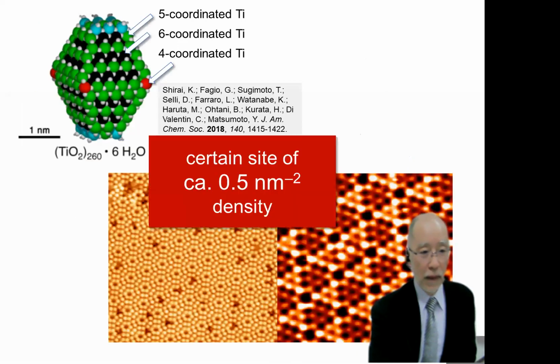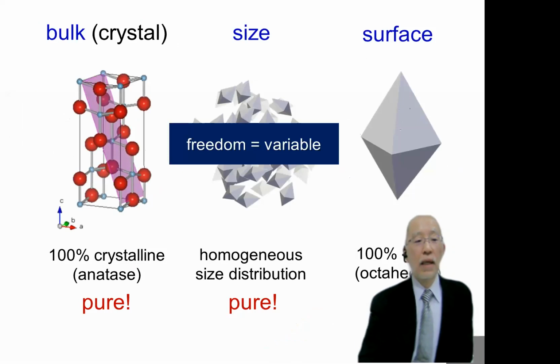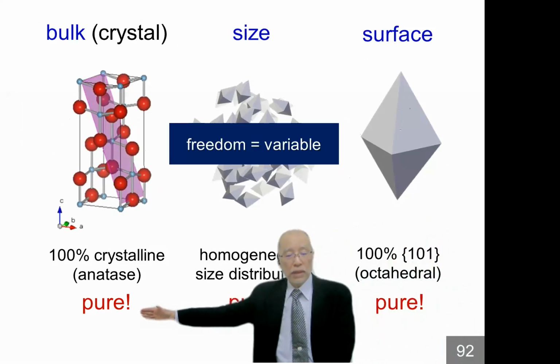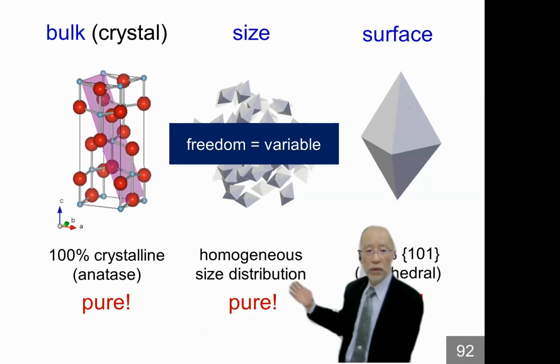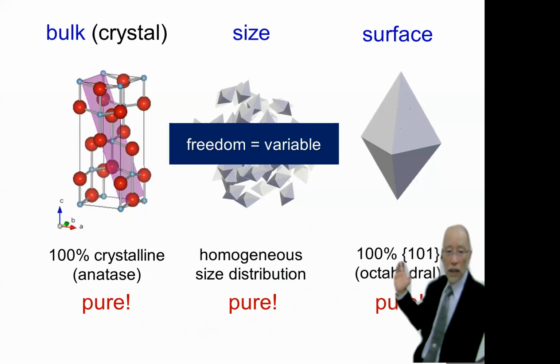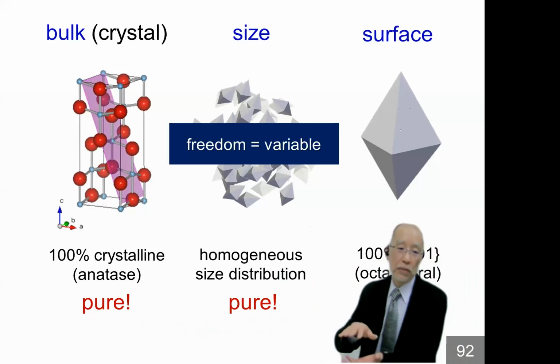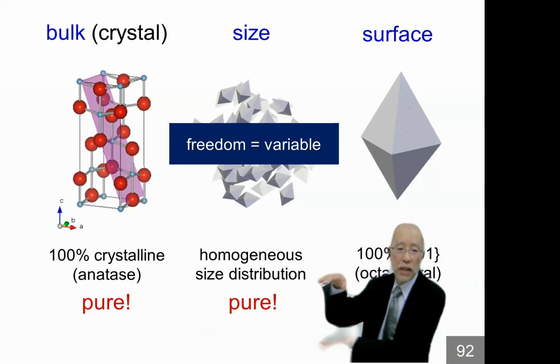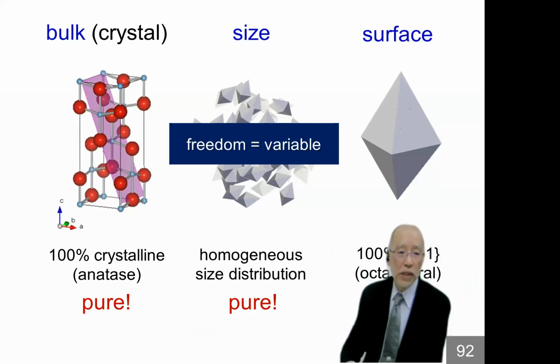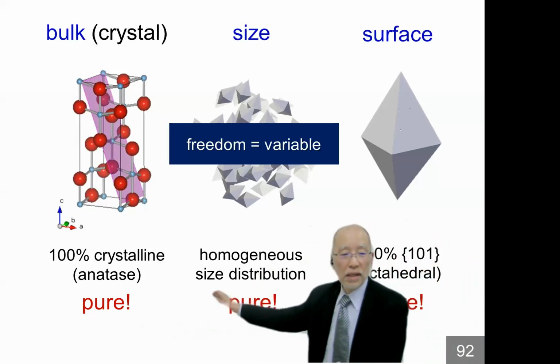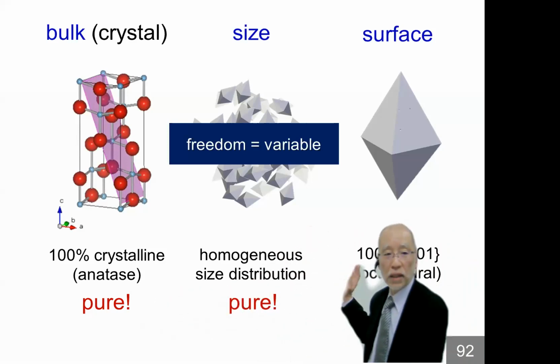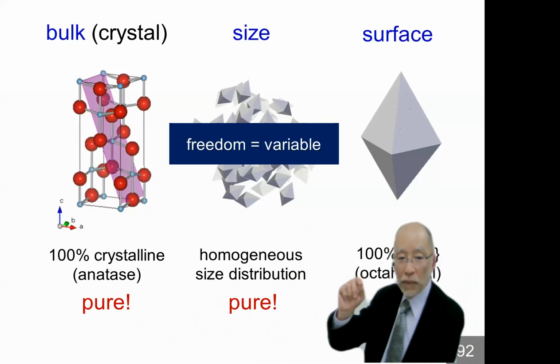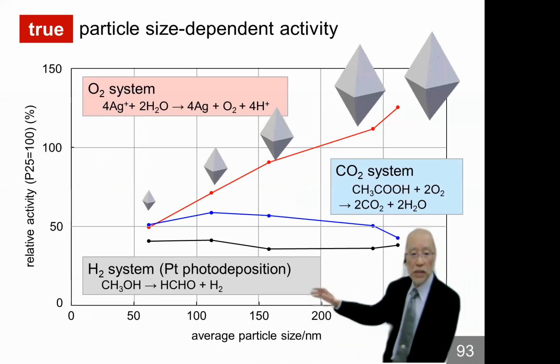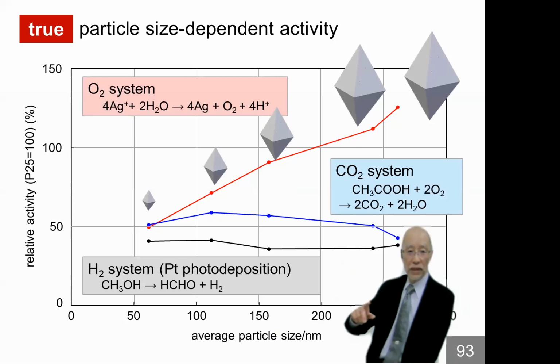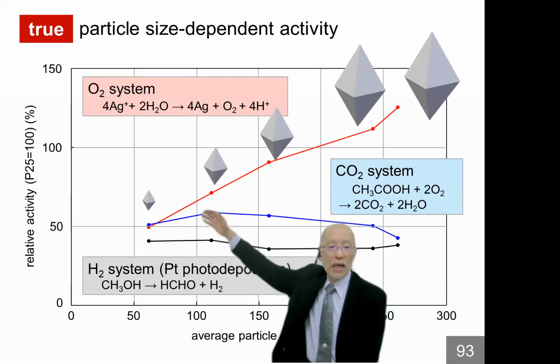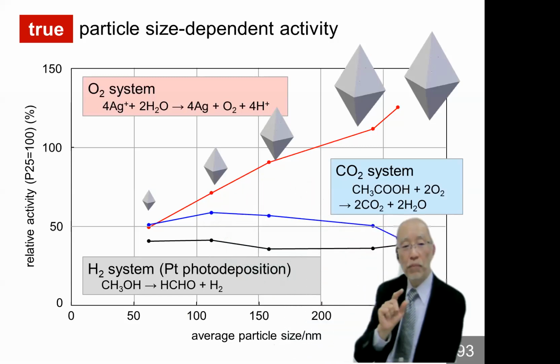And then we obtain almost 100% anatase bulk crystal and almost 100% surface 101. But the particle size can be changed. That is variable. Even if that is pure, one size, the other, another size. So there is freedom for size. So by changing only the size, without changing bulk structure and surface structure, we can see the difference in property depending on the size. And this is the actual result for 3 kinds of photocatalytic reaction. And surprisingly, for the oxygen evolution reaction case, the activity is increasing almost linearly with particle size.